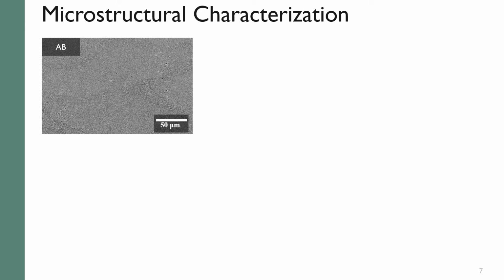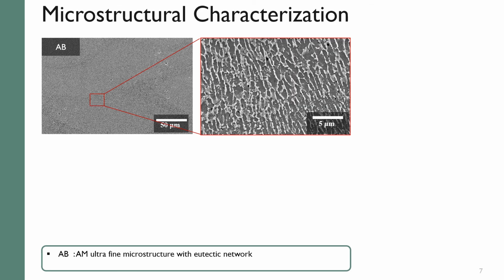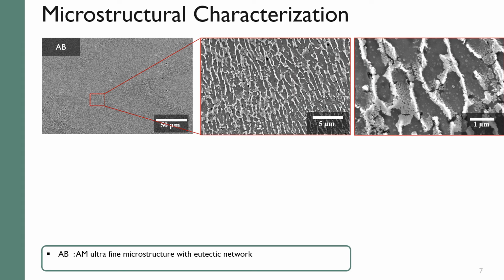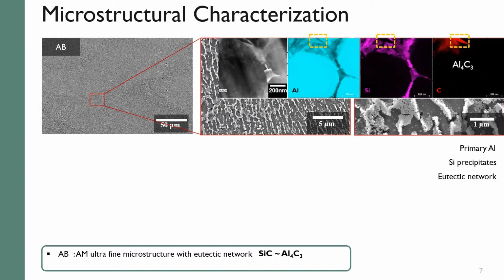In this SEM image, ultrafine as-built microstructure is shown, and if we zoom in, fine silicon precipitates within the primary aluminum grains, which are surrounded by aluminum silicon eutectic network, can be seen. Also, by TEM, it is shown that silicon carbide reacted with liquid aluminum and formed aluminum carbide in our case.